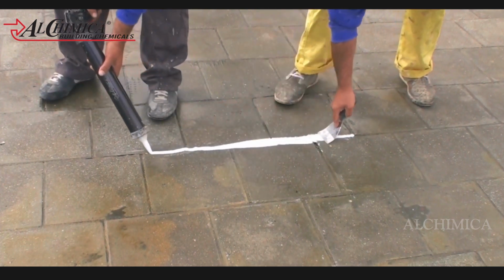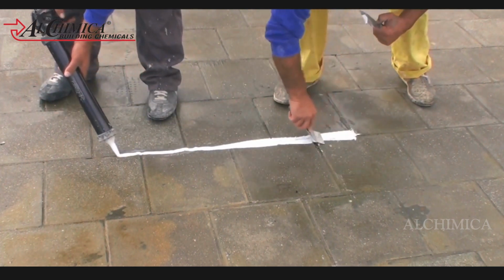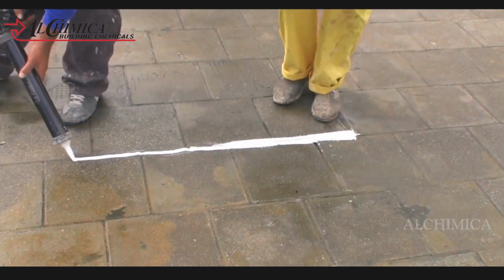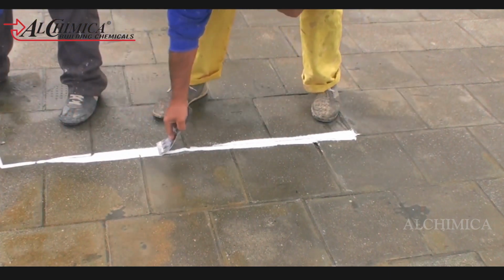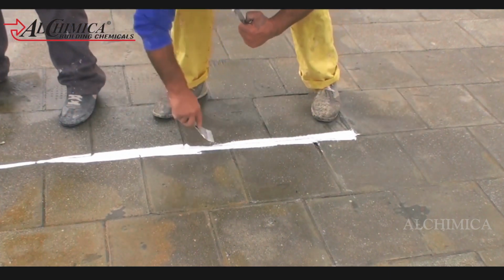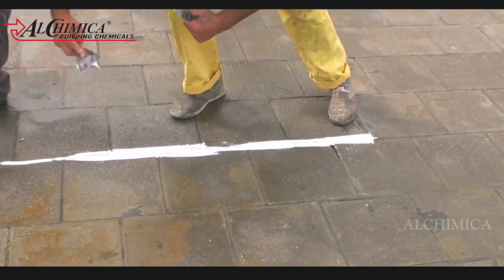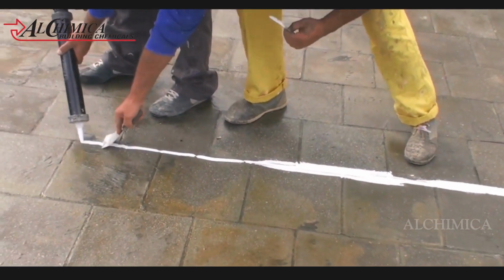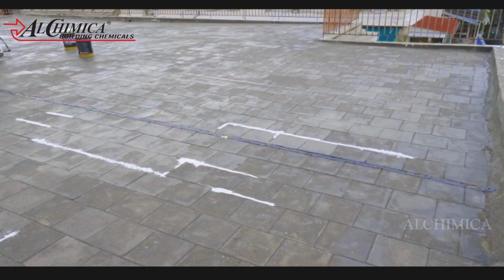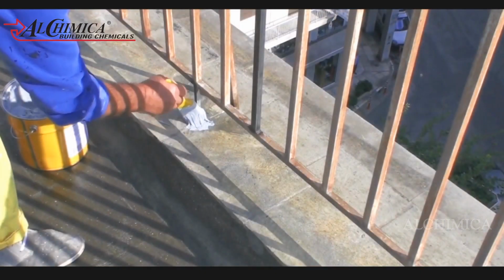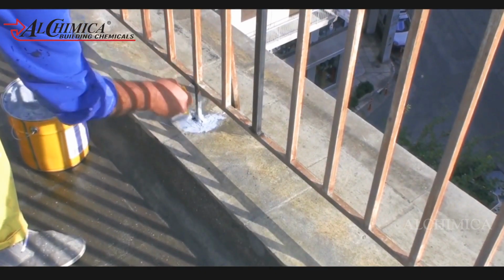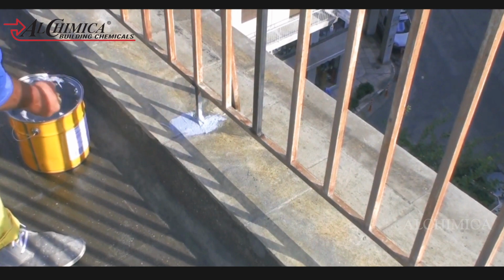All cracks are opened to V-groove and joints are treated with polyurethane-based sealant by spatula. Wide cracks are filled with special repair mortar Hygrosmart fiber. All penetrations and upstands have to be coated with a coat of Hyperdesmo coating by use of a brush.